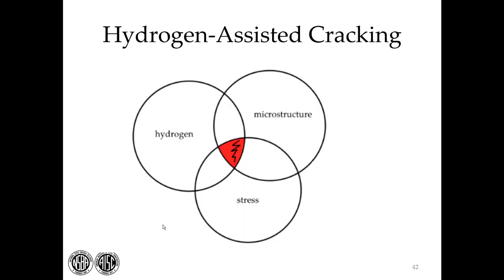So to get cracks from hydrogen, or what we call hydrogen-assisted cracking, you need to have the right combination of hydrogen, stress, and microstructure. But this is where the code helps you out, and steel welding practices help you out. The primary way to avoid a susceptible microstructure is to use the right material. Modern bridge steels are designed and established under D1.5 to be highly weldable, or to avoid a susceptible microstructure. This is also spoken of in terms of hardness. How hard is the microstructure? Historic steels can be much more questionable in terms of how hard they are.